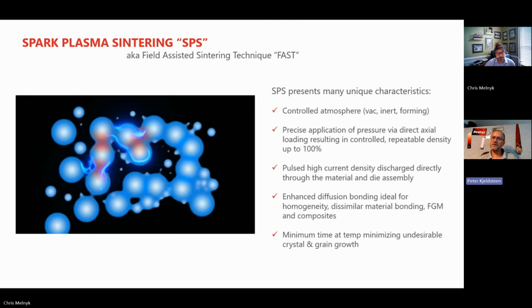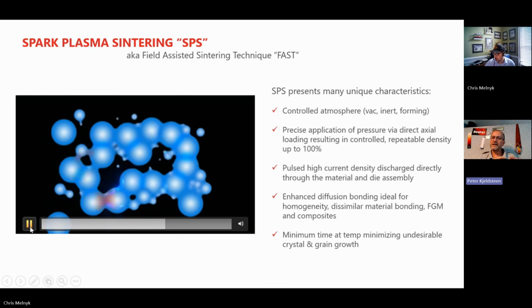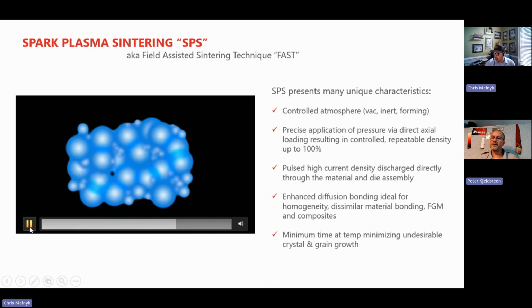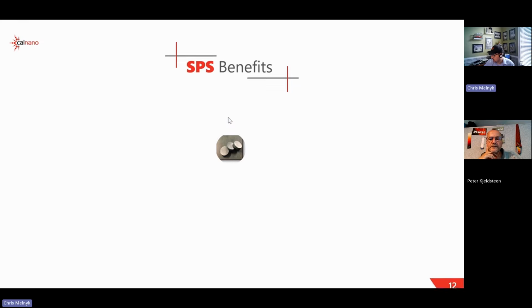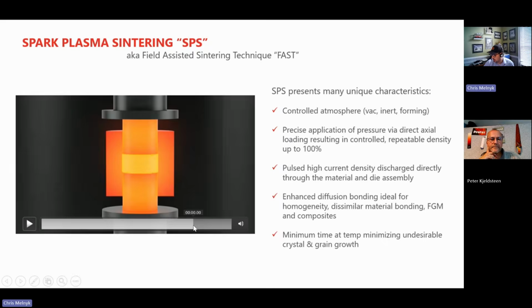So when you don't have that, if you have a ceramic, will you introduce the heat through the die? You heat the die instead. Absolutely. So in that case, the heat is not as central. The heat is coming mostly from the die to start with, as the current will go through the die. Most of the time the tooling is graphite, not exclusively, but a lot of times it is. So it is a conductive path as well.